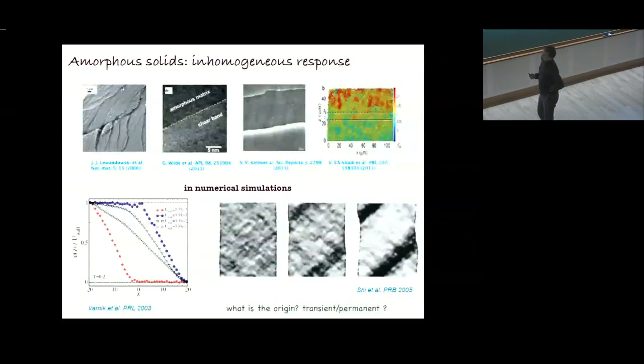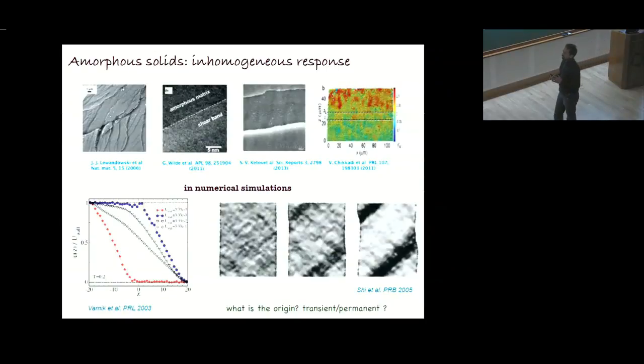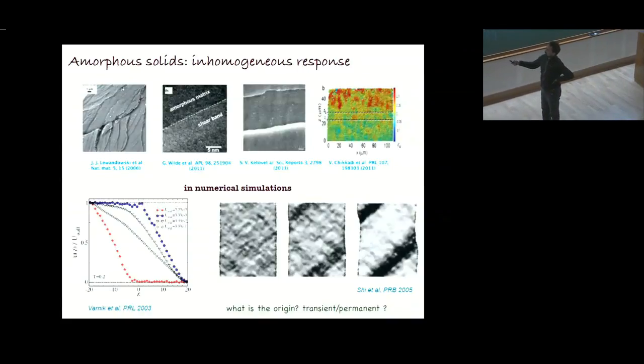So why are we interested in this problem? In a lot of materials, when this glass is subjected to some mechanical perturbation, you see these kind of heterogeneous responses appearing in the material. These are metallic glasses, different metallic glasses which have been deformed. When you stop the deformation, you see that there are some regions which have deformed more than the others. These are known as shear bands, and these can be very narrow or very wide depending upon ambient conditions. On the other hand, a colloidal glass, when one deforms this colloidal glass, you have a region which is flowing more than some other region.